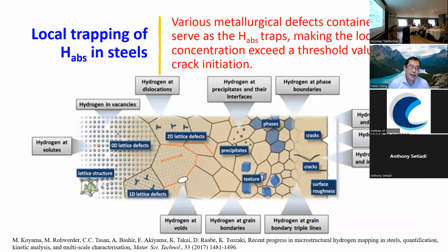Anyhow, if hydrogen does go into the steel, I just comment that there are lots of hydrogen traps that can make the hydrogen accumulate and reach a high concentration. For example, in the steel there are grain boundaries, dislocations, vacancies, inclusions, precipitates and second phase particles. All of them can serve as effective hydrogen traps. So if the local hydrogen concentration reaches a certain threshold value, combined with stress and certain steel metallurgy conditions, we say the cracks can be initiated.